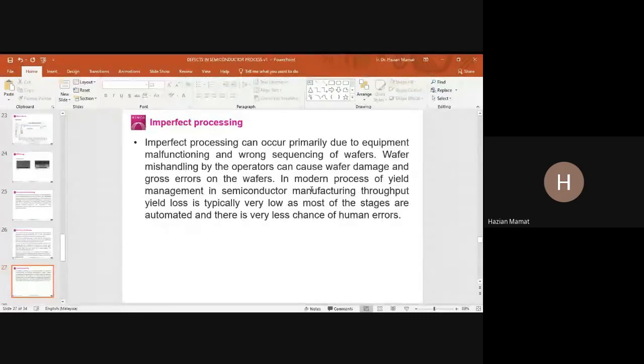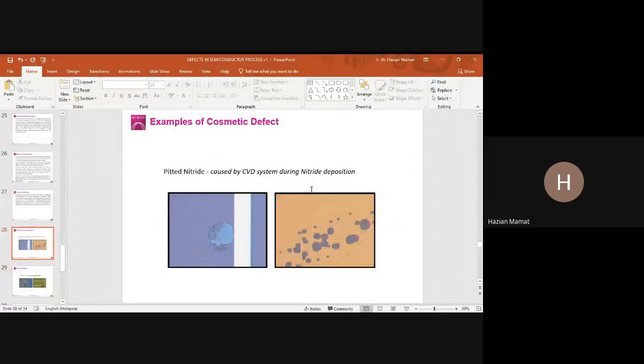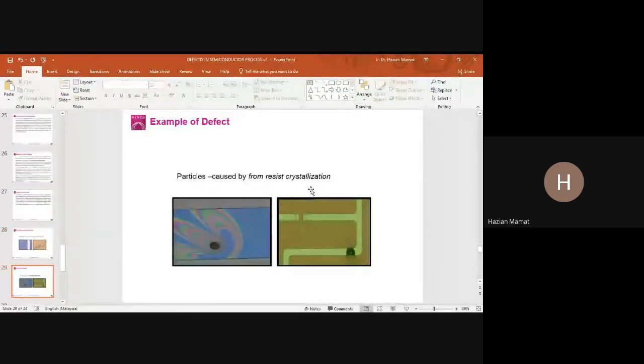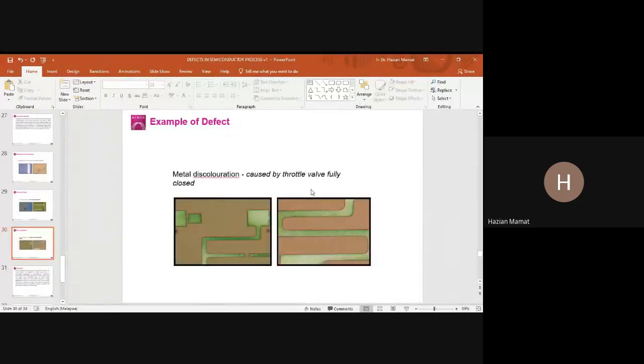This is an example of a cosmetic defect. This is pitted nitride, which is caused by the CVD system during the nitride deposition. And this one is particles caused by resist crystallization, resist not fully removed from the process. And then this one is metal discoloration, which is caused by the throttle valve fully closed during the process of metal deposition.